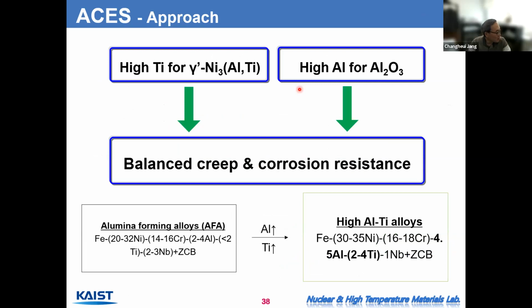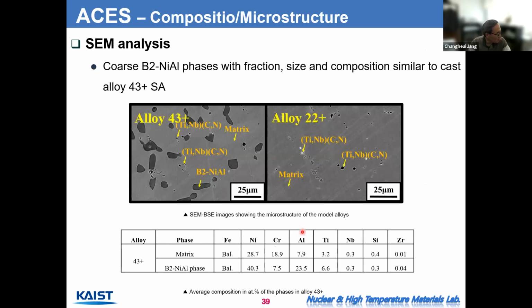So our idea is that for the improvement of the high temperature oxidation resistance, we try to increase the aluminum content and also try to add more titanium to have a better creep resistance. But it is well known that titanium is bad for high temperature oxidation. So we wanted to balance the amount of titanium and aluminum to have a balanced creep and corrosion resistance. So we increase both aluminum and titanium together to have a better combination of creep and corrosion resistance at high temperature. So this is one of the alloys that we developed. We have roughly 4.5% of aluminum and 3.6% of titanium here. And this one has a little bit lower content of aluminum and titanium.